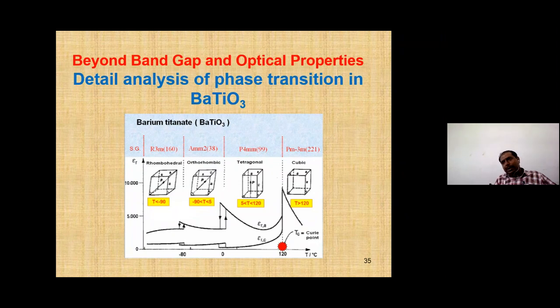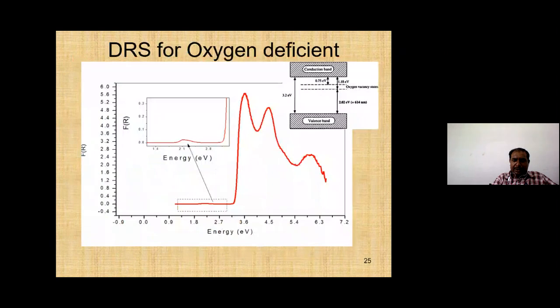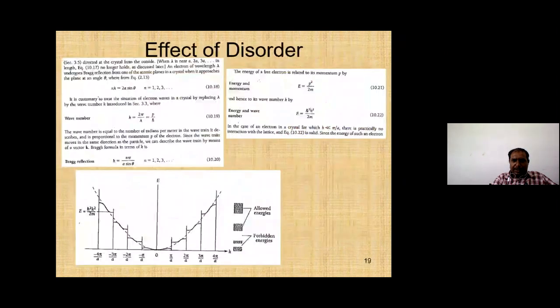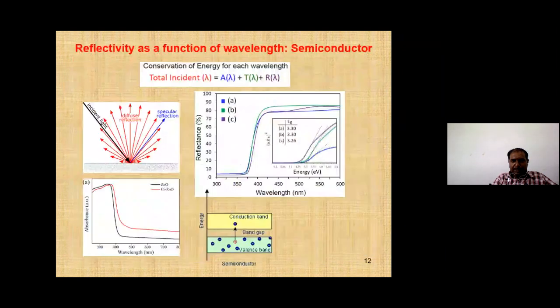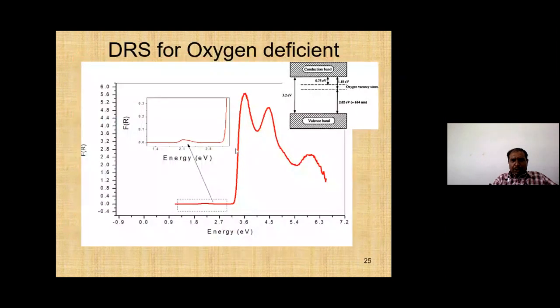As a result of that, this particular optical absorption spectrum will not be sharp, but will be something like this. So from this particular slope, in fact, we have given one model. What you can do, Alka, is that I can share one paper, our recent paper, where we have used optical absorption spectroscopy to estimate the particle size distribution. I can share that paper with the candidate and with all of you. As I said, from this particular slope, we have given one model to estimate the particle size.